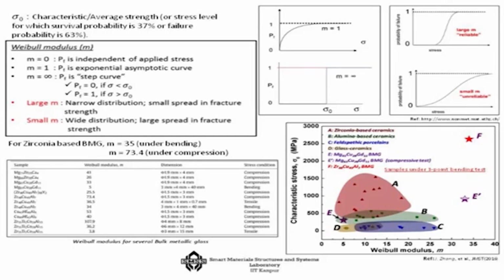Large m essentially means that there is a narrow distribution of the property. That means the particular property is very crisp, we call it a crisp probability. That means the material property variation range is very small. On the other hand, a smaller m means a wider distribution, a larger spread in fracture strength. So, here, as you can see, as the Weibull modulus is increasing, these points are coming together.